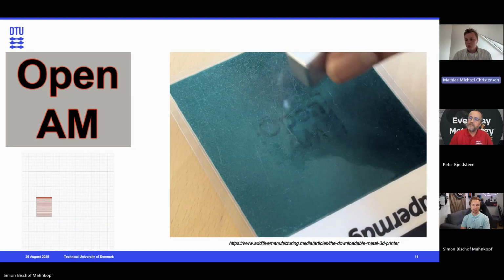So essentially, to build upon that, you can see here on the right-hand side picture this OpenAM logo, which is being seen through magnetic viewing film and a magnet, to be able to print that text where you have a martensitic phase that's ferromagnetic and the rest behind that is a bulk paramagnetic. It looks similar to the metal top view picture we have on the left. But in order to print that, you do it sequentially.